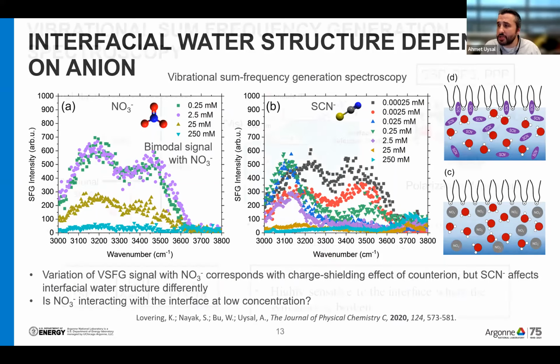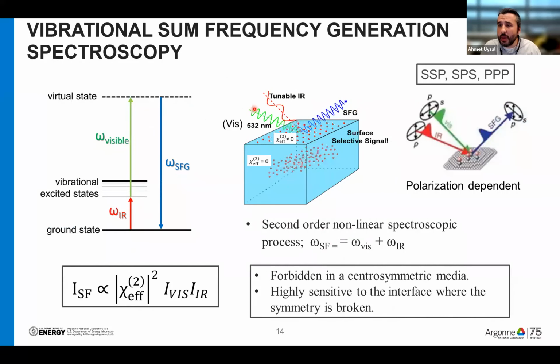But before showing that, let me just mention what we are doing in SFG experiments. We have a picosecond laser, actually two laser beams coming on the surface. One is a fixed 532 picosecond laser, and another one is a tunable IR laser. We overlap them at the surface spatially and temporally. And then they generate a sum frequency photon in a nonlinear process. And this nonlinear process is forbidden in a medium which has inversion symmetry. But the interface naturally doesn't have that inversion symmetry. So our SFG signal is very surface specific.